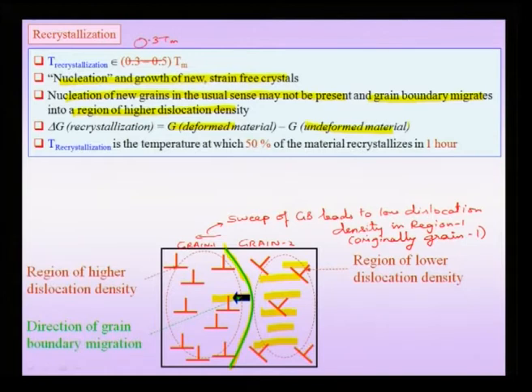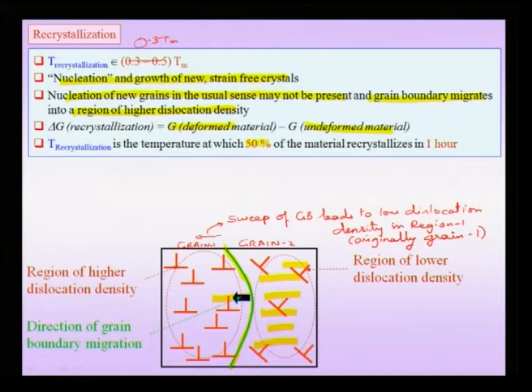There is a temperature which is defined in this context, which is called the recrystallization temperature, because suppose I am using recrystallization as an intermediate step during some kind of a mechanical working process like forging, then I need to hold my material at a certain temperature so that I have a significant amount of softened material which can take further deformation without cracking. So the recrystallization temperature unfortunately is a slightly notional term, which involves both percentages and time in its definition. The temperature of recrystallization is the temperature at which 50% of the material recrystallizes in 1 hour. That means the definition involves both percentages and time.